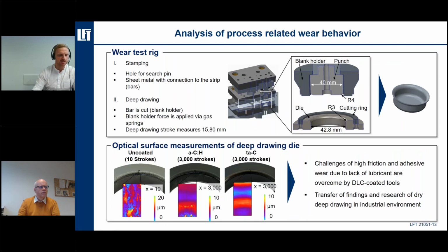So in the laboratory test, it was proven that the a-C:H and the ta-C coatings reduce friction as well. However, the laboratory tests only investigate the tribological behavior for a lower number of forming operations. Therefore, the durability of the modification has to be investigated for a higher number of forming operations. The drawing of rectangular cups, which we had seen before, is not suitable for this purpose because it is not capable of producing enough formed parts. So this motivated us to develop a novel test rig based on a high press speed. In this regard, you can see our tool, a follow-on composite tool, was used. The advantage of this kind of tool is that there are short cycle times and high quantities can be achieved.